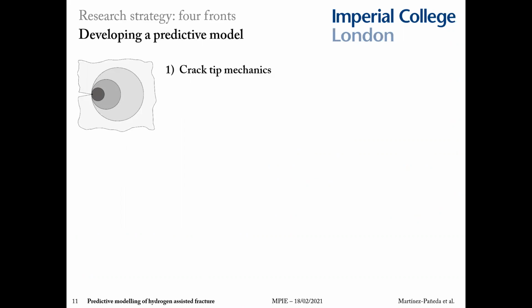First, it is important to precisely characterize the stresses ahead of the crack. And this is not only relevant because brittle failure will occur at a critical stress, but because, as I mentioned before, hydrogen accumulates in areas of high hydrostatic stress.